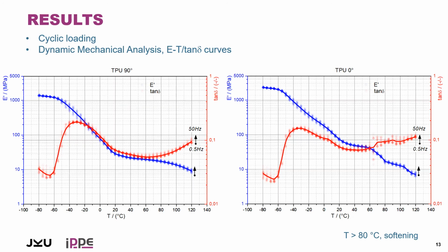And from the monotonic test, we moved to the more interesting cyclic test. And as I mentioned, I would like to characterize the deformation behavior, and due to the inherent viscoelasticity, we need the viscoelastic parameters. First, conventionally, we performed dynamic mechanical analysis tests and determined the E prime, does it mean the storage modulus, and also the loss modulus, and then tangent delta values for both materials. Here I am showing the thermoplastic polyurethane for both printing orientations, the 90 and the 0.